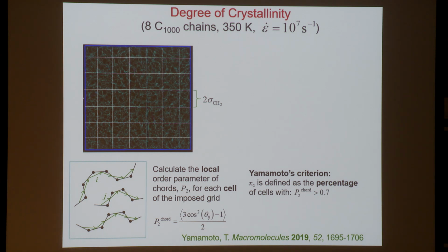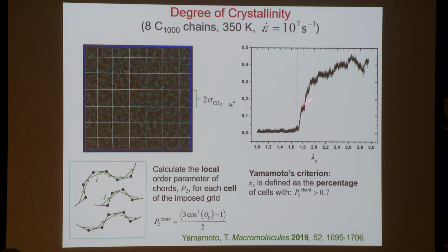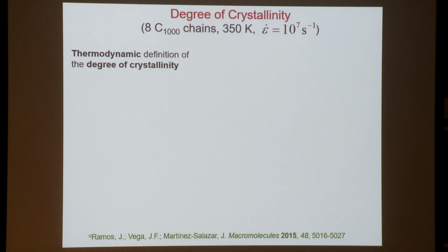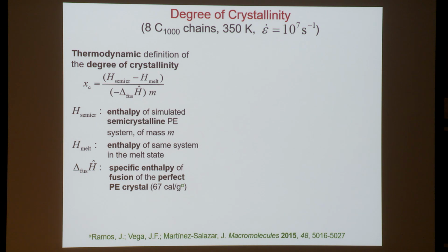Otherwise, it is amorphous. So based on this definition, here's how the crystallinity, the degree of crystallinity, evolves with the stretch ratio during this drawing process that I showed you. Originally, it is 0, and it remains so during a long incubation period. But then one has nucleation and growth of the crystalline lamella, leading to something like a 0.45 crystallinity in the ultimate system. One can adopt a different criterion for crystallinity, for example, work with the enthalpy rather than with orientation.